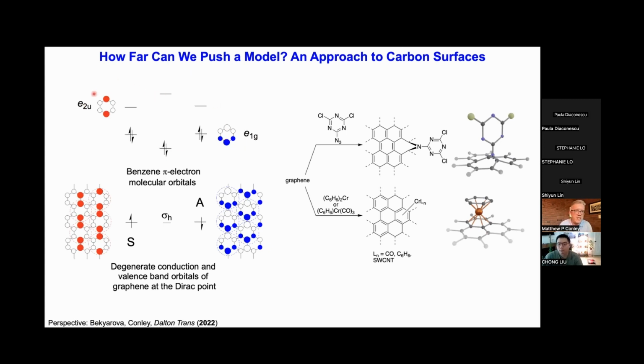So if you basically take the E2U and the E1G orbitals of benzene and you put those into a band type structure, these are the orbitals you would get for graphene, which are degenerate because you have no band gap at the Dirac point. So that can explain why most of the organic functionalization chemistry introduces defect sites at well-defined positions because of the orbital population in these two states.